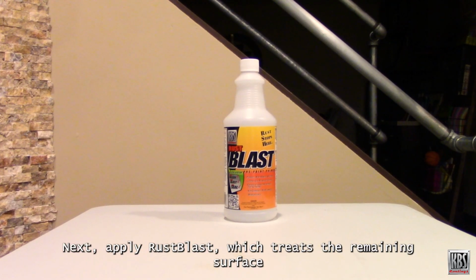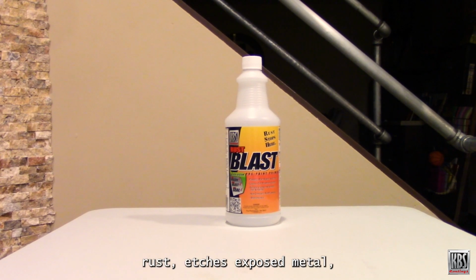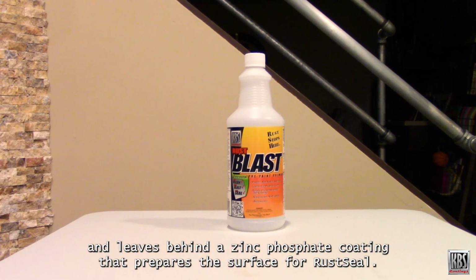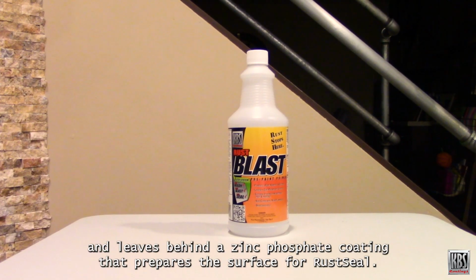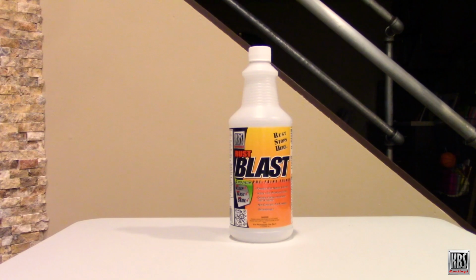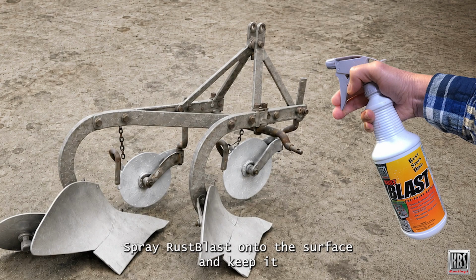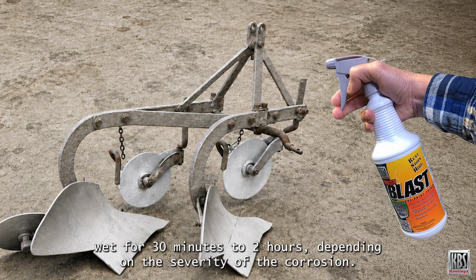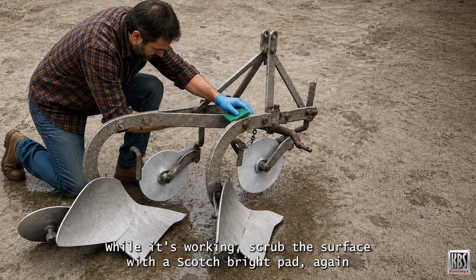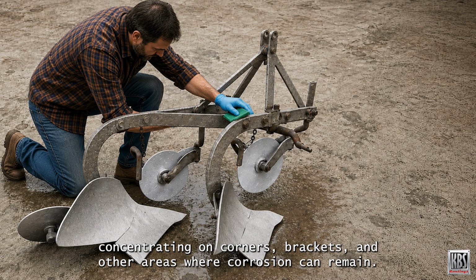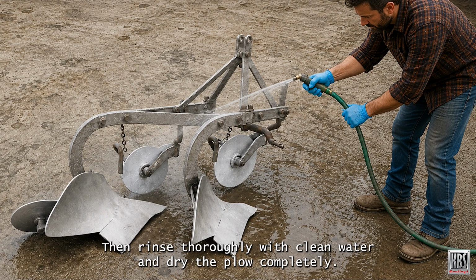Next, apply RustBlast, which treats the remaining surface rust, etches exposed metal, and leaves behind a zinc phosphate coating that prepares the surface for RustSeal. Spray RustBlast onto the surface and keep it wet for 30 minutes to 2 hours, depending on the severity of the corrosion. While it's working, scrub the surface with a Scotch-Brite pad, again concentrating on corners, brackets, and other areas where corrosion can remain. Then rinse thoroughly with clean water and dry the plow completely.